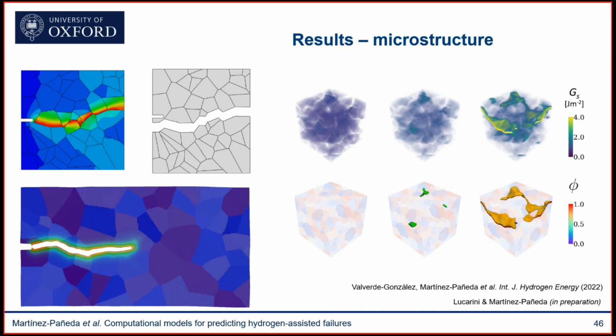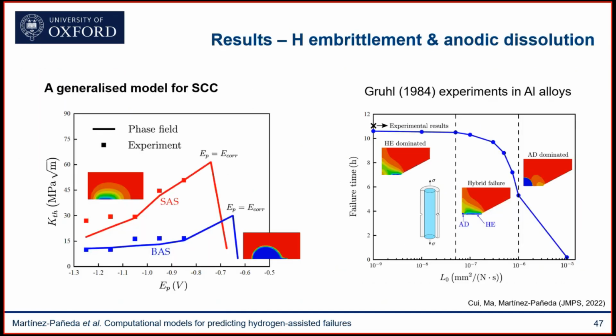But we can extend these models to capture the role of the microstructure, and you can see some examples here where we're simulating in 2D and 3D the propagation of cracks while resolving the anisotropic nature of the microstructure. We have also combined this with those phase field corrosion models that I was talking to you about before. And this is quite powerful because it allows us to develop generalized stress corrosion cracking models. And these are models where we don't have to make any a priori decisions on which is the mechanism dominating the cracking process.